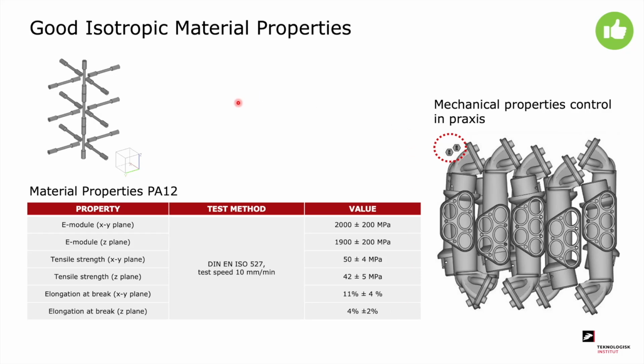If we take a look at the picture to the left, we have printed some tensile bars. This is the way we typically quantify the material properties: printing these bars, testing them, and documenting that we have good and uniform properties. When we do this on a daily basis, we always place the test pieces in the corner of the chamber. We do that because potentially this is where we have the lowest temperature, which can lead to the weakest points. So by putting the tensile bars there, we make sure we have a worst case scenario. When we print tensile bars on each build job, we always make sure we have good quality and can always document what the properties are.